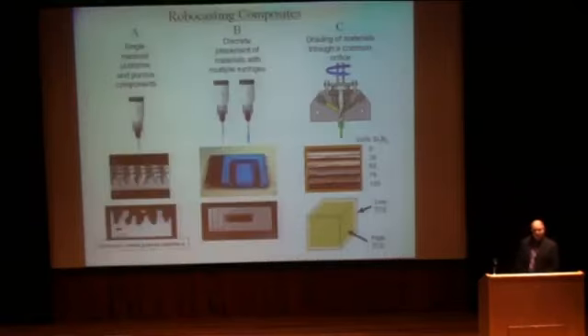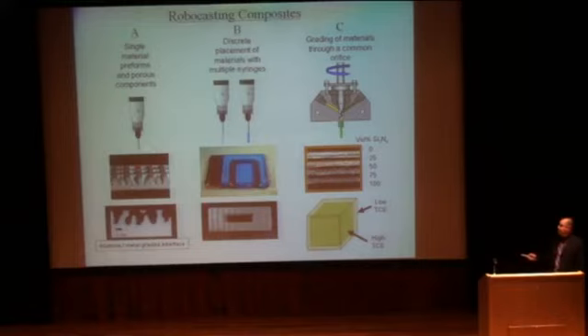But the other thing that robocasting has the capability to do, which might have commercial relevance, is making composites. You can make composites by either making a preform with just one material and then infiltrating the second material. Or you can use two discrete materials, where you can put an electronic circuit buried into some other material. Or you can have a fugitive material that is then burnt out so that you can make channels inside the part. Or you can take it further and have controlled ratios of multiple materials.